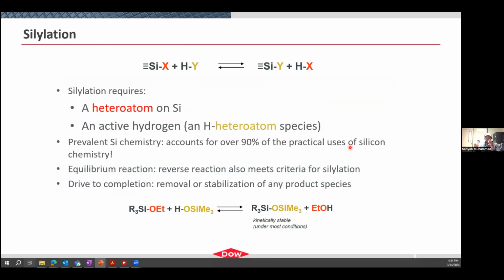Silylation essentially is just transferring a silicon group onto another group. So you start with two species. One of them is a silane or silicone-based material with a heteroatom that is different than the heteroatom on a species with an active hydrogen source. And we'll get into some examples here. What happens is you have this equilibrium reaction where you are swapping out these two heteroatoms such that you essentially install this heteroatom on this silyl group here. This type of chemistry is the most prevalent when we think about silicon chemistry, and is what we use every single day. Because it's an equilibrium reaction, you often have ways to drive the reaction to favor one side and drive it to completion.